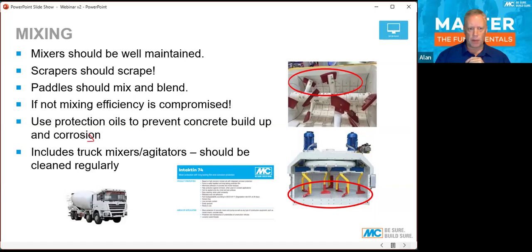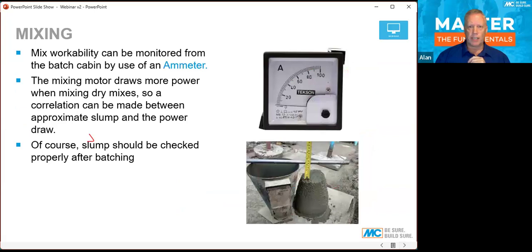Another trick that many people use around the world for monitoring the quality of concrete is to use an ammeter. Now, I don't know if you have in your plants, maybe you have seen this trick used, and it's basically that as the mixer is turning, it draws power, and therefore it registers on an amp meter. A wetter concrete draws less power than dry concrete. So the amp meter can be used as a tool. It can give an indication of the workability. And when the needle stabilizes and not moving around, that can indicate that proper mixing is achieved.